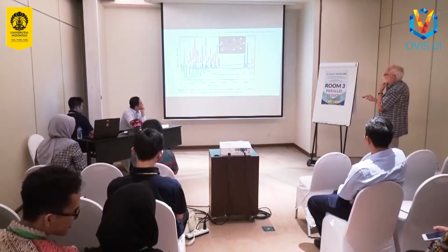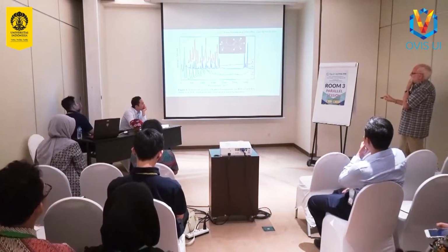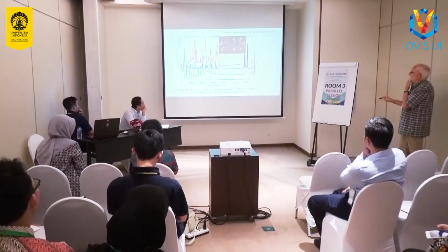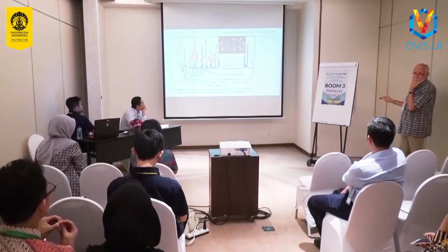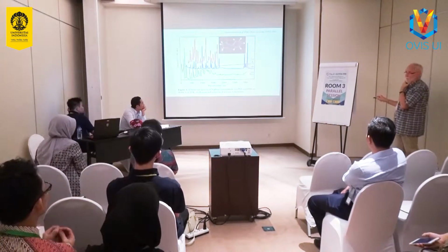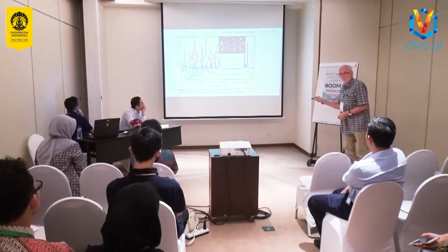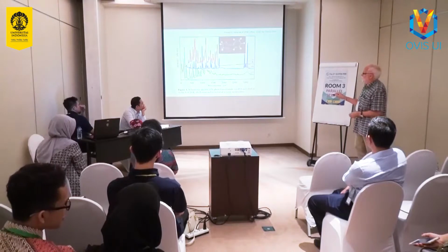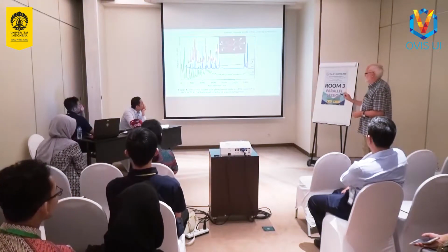You'll also see what I referred to earlier about the poor resolution at high wave number. On this particular spectrometer, which was TOSCA, the CH stretching region is very poor in neutrons. Much better to do infrared or Raman if you're interested in those vibrations. But down here, we've got all of this region accessible to us with neutrons, and we'll see all the vibrational modes that involve the motion of hydrogen atoms.